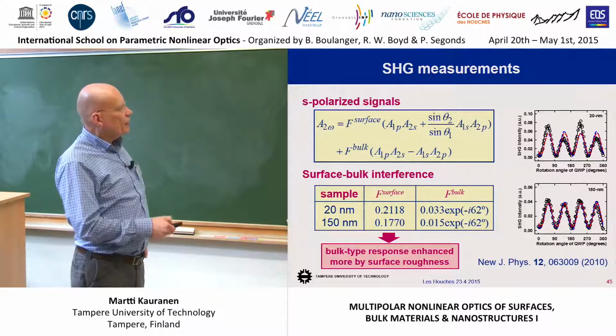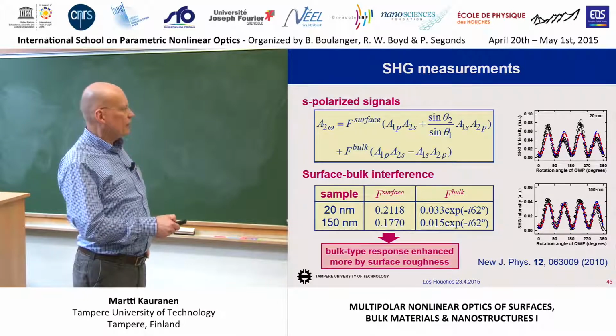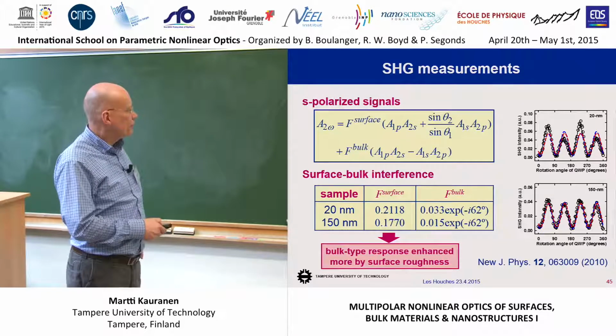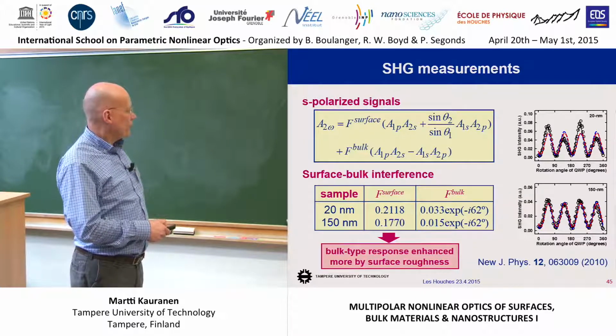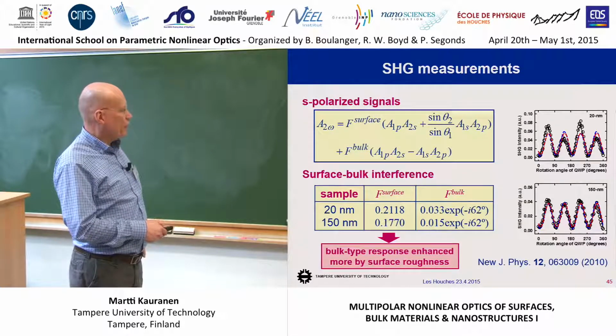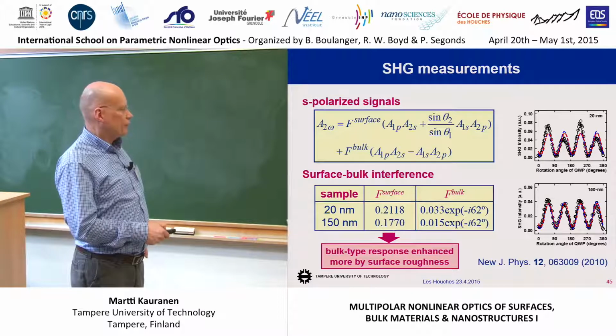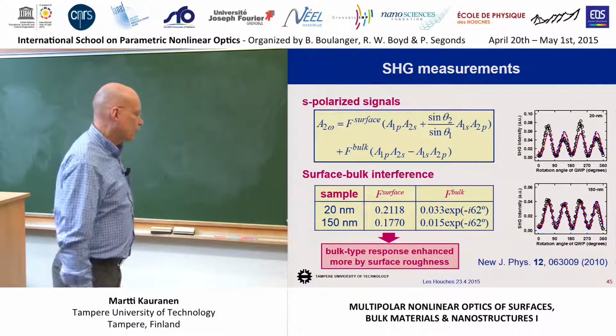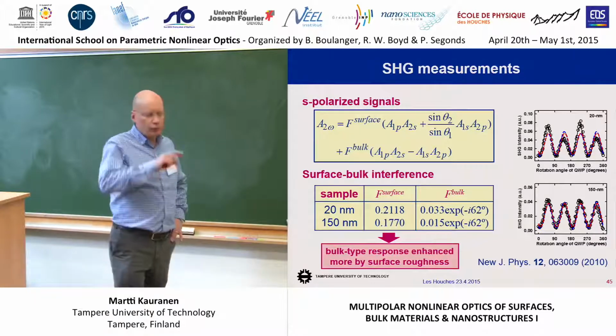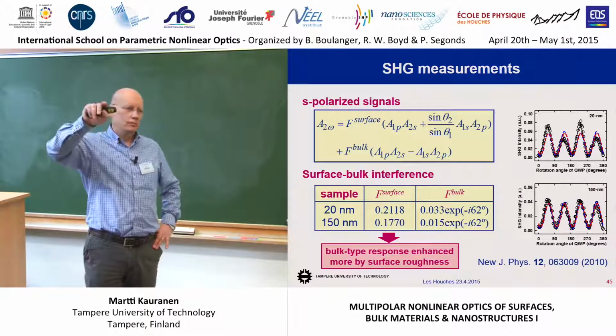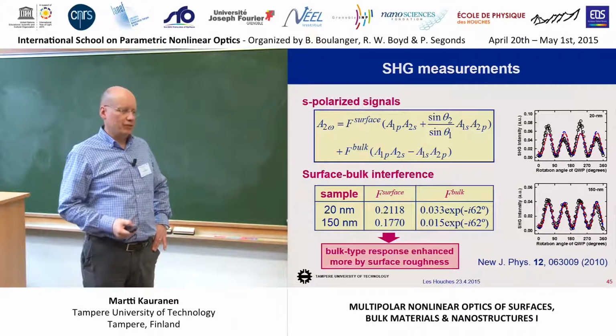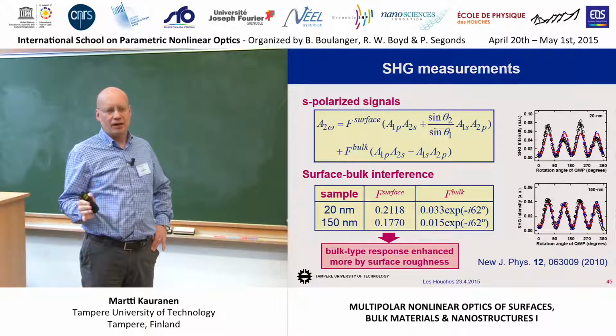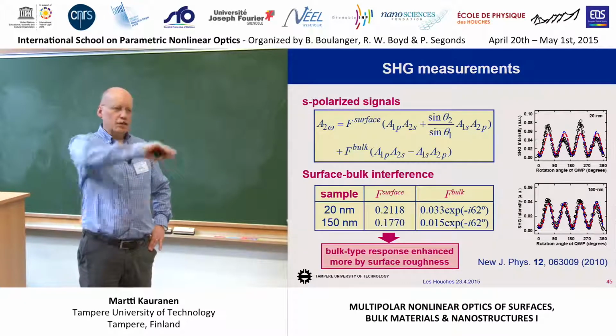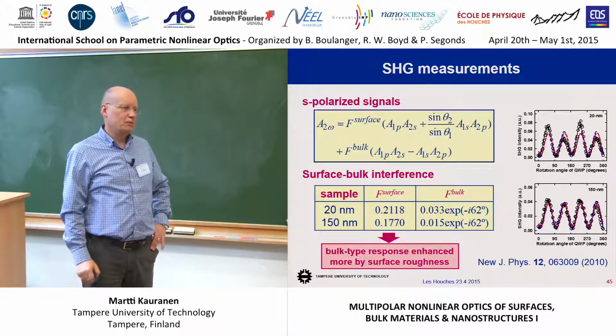So here we see that the deviation from any possible surface response is even higher. And when we fit the data here using this simple model, then when we have a rougher surface for the thin sample, the surface parameter goes up by about 10%. The bulk response is more than doubled. So this is strange, where basically we think that we are modifying the surface structure, but it seems that the bulk response goes up. So something really strange is happening here. How is this possible? We change the surface, but the bulk response seems to go up.